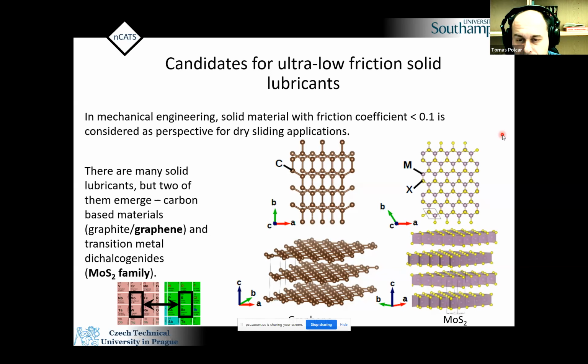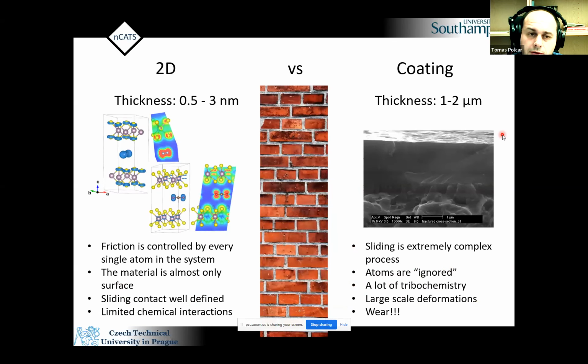And that's how I started research. There are two problems, though. If you look at 2D materials, which are absolutely fantastic because this is a very well-defined system, in tribology you look at every single atom, you understand its role, and the material is just surface. Typically, we don't care much about bulk effects, like grain boundaries or plasticity. So it's a kind of minor issue here, and the chemical interactions are very limited. If you use these materials in a real application, let's say a bearing, then of course you need much thicker materials, and then sliding is extremely complex, and there is tribochemistry, oxidation, large-scale deformation, so it's very, very difficult to really understand the problem.